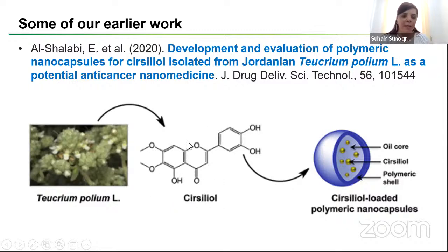It's a plant common to the Mediterranean region, and she isolated a bunch of compounds, one of which is cirsiliol. But basically, there has been no publication or study where this compound, although it had promising anti-cancer activity, was formulated into any type of dosage form. So we made it as polymeric nanocapsules with an oil core and a PEG-PCL shell, and we characterized this nanoparticle formulation and its bioactivity in cancer cells as well.